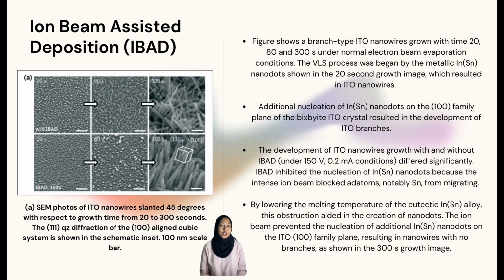electron beam evaporation conditions. The VLS process was begun by the metallic In-Sn nanodots shown in the 20-second growth image, which resulted in ITO nanowires. Additional nucleation of In-Sn nanodots on the 100 family plane of the bixbyite ITO crystal resulted in the development of ITO branches. Nonetheless, the development of ITO nanowire growth with and without IBAD differed significantly.